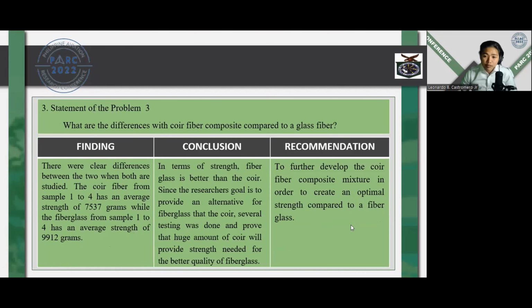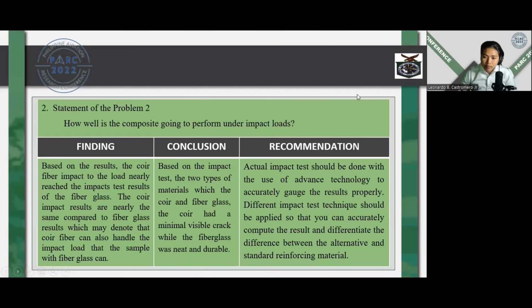Statement of the problem number 2. How well is the composite going to perform under impact loads? Findings. Based on the result, the coir fiber under impact load nearly reached the impact test results of the fiberglass. The coir impact results are nearly the same compared to fiberglass results, which may denote that coir fiber can also handle the impact load that the sample with fiberglass can.